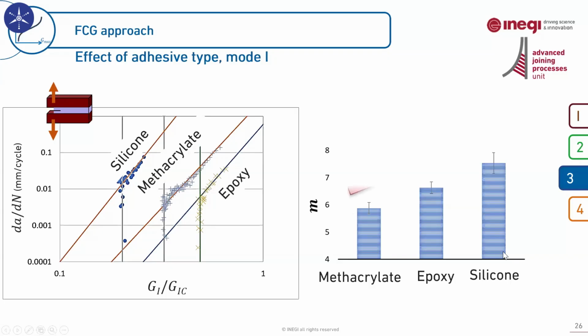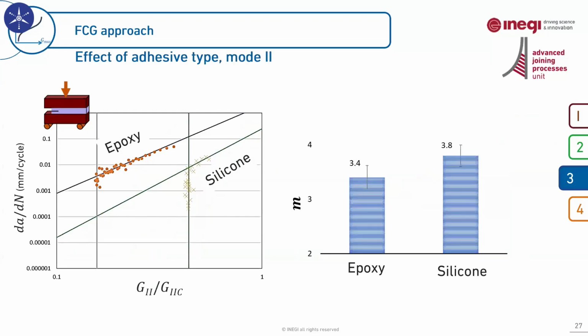But as a general trend, we can say that the lower the mode 1 fracture energy under quasi-static loading condition, the higher the M value under cyclic loading condition. A similar conclusion holds for pure mode 2 loading, where we use the ENF joints for fatigue crack growth under mode 2 loading condition. And again, we can say the lower the mode 2 fracture energy under quasi-static loading condition, the higher the M value under fatigue.